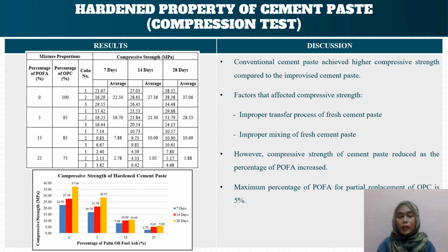These factors will cause the components of materials of cement paste to be isolated from each other, therefore it decreases the compressive strength. However, by comparing the compressive strength of the improvised binder, it is found that the compressive strength will be reduced as the percentage of POFA increases. Therefore, it can be concluded that the maximum percentage of POFA for partial replacement of OPC is only 5%.